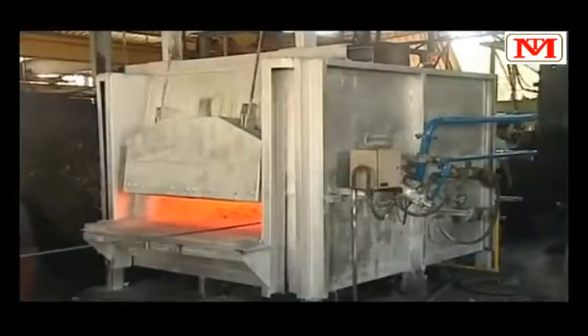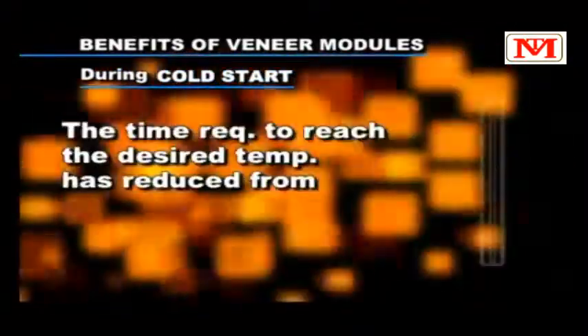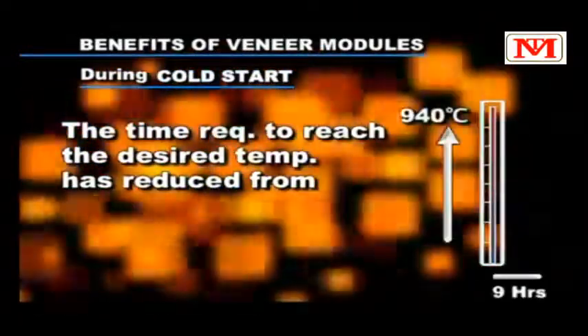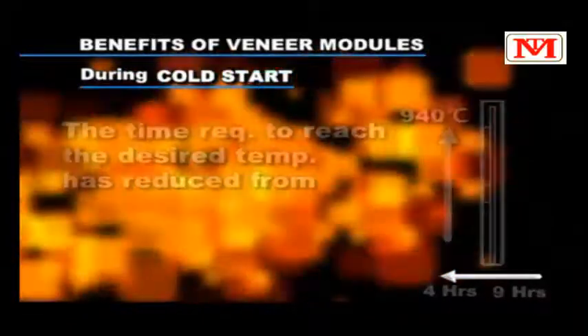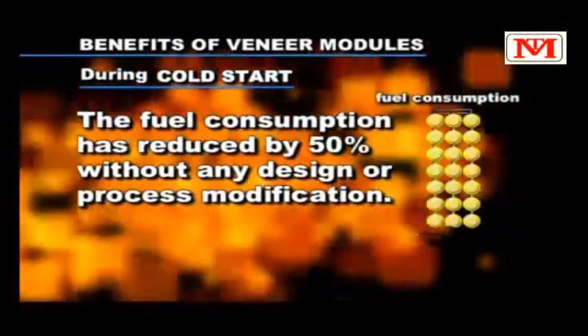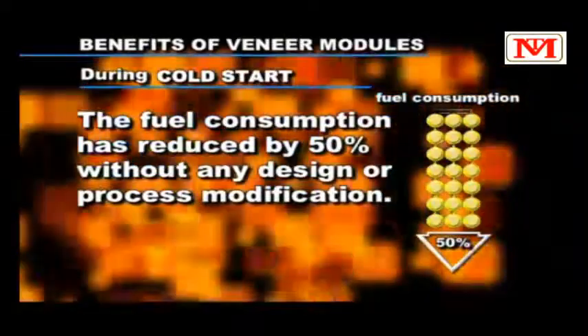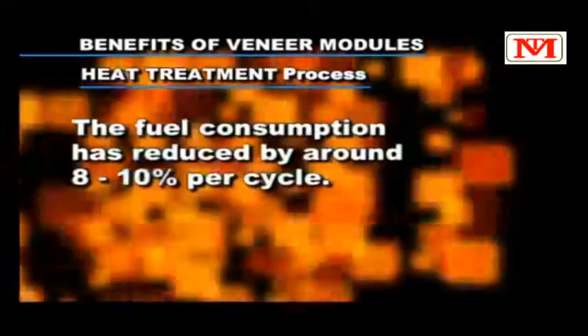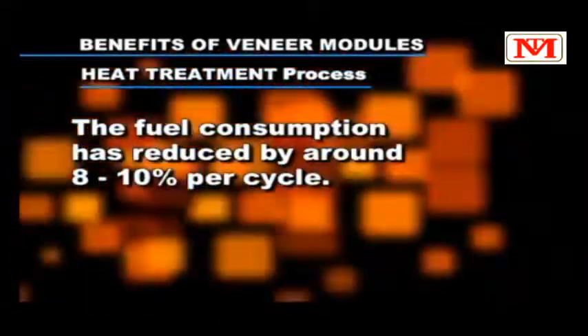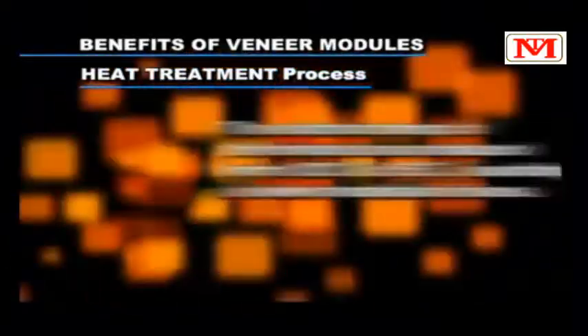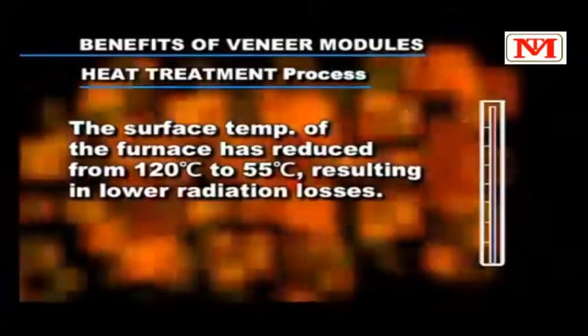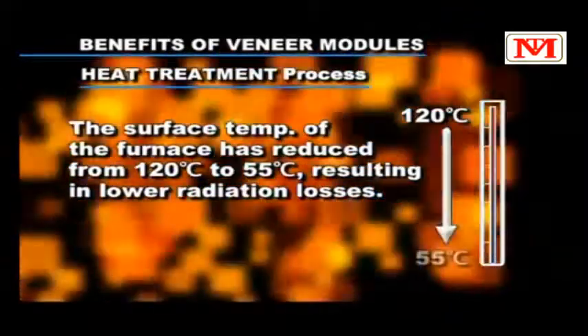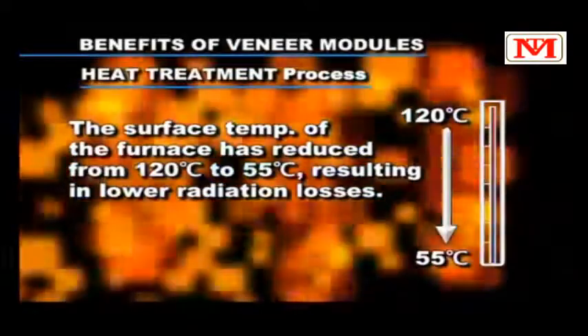Based on the trials carried out after implementation, the benefits accrued are manifold. During cold start, the time required to reach the desired temperature has reduced from 9 hours to 4 hours. The fuel consumption has reduced by 50% without any design or process modification. During heat treatment process, the fuel consumption has reduced by around 8 to 10% per cycle. The surface temperature of the furnace has reduced from 120 degrees Celsius to 55 degrees Celsius, resulting in lower radiation losses.